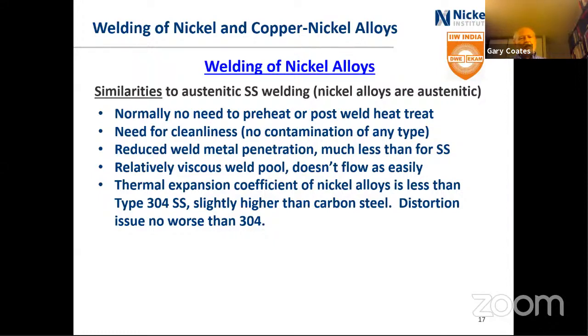The thermal expansion coefficient of nickel alloys is less than 304, so slightly higher than carbon steel. So distortion is no worse a problem on nickel alloys than it is on 304. You can treat them about the same, even though actually the thermal expansion coefficient is less there.